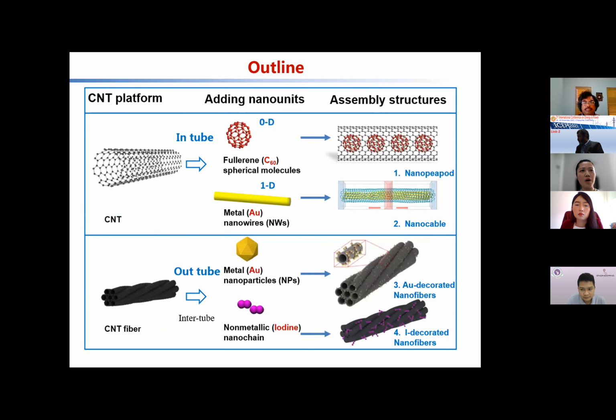In this talk, our material platform is adding zero-dimensional spherical fullerene molecules and one-dimensional gold nanowires into the tube. On the other hand, decorating gold metal nanoparticles and non-metallic iodine nanochains onto the CNT fiber. It is out of the tube versus in the tube. That is, we have 4 kinds of assembled structures. The contribution of nano units to thermal, not electrical, transport is our main concern. The first 2 kinds of assembled structures are studied by molecular dynamics simulation due to experimental difficulty. The last 2 are studied experimentally and theoretically.